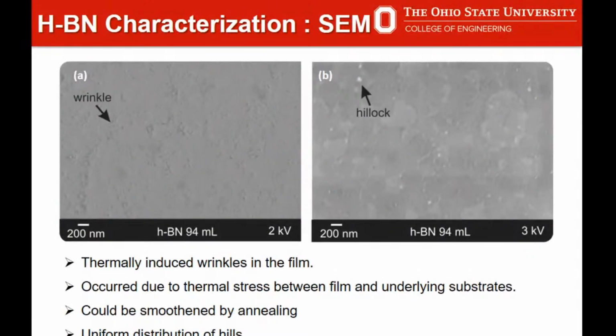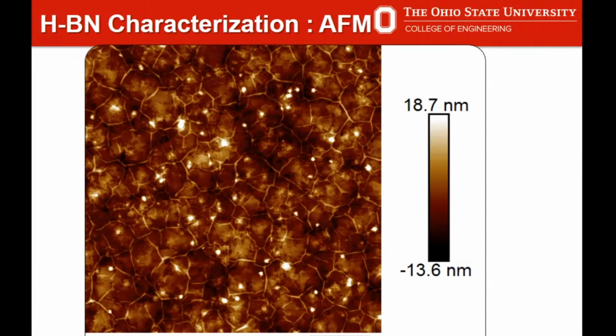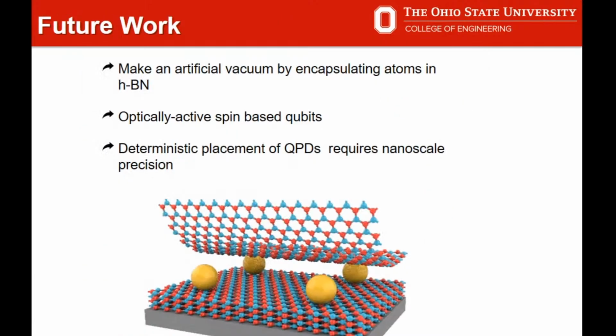For surface morphology, we have used scanning electron microscope, and lots of wrinkles are found here, as you can see in figure A, and some hillocks are there. Wrinkles can form because of the thermal expansion mismatch between the substrate as well as your film. And this is the AFM. AFM images show you how the wrinkles are there. Lots of wrinkles and hillocks are there, and the scanning range of the AFM is around 1 micron.